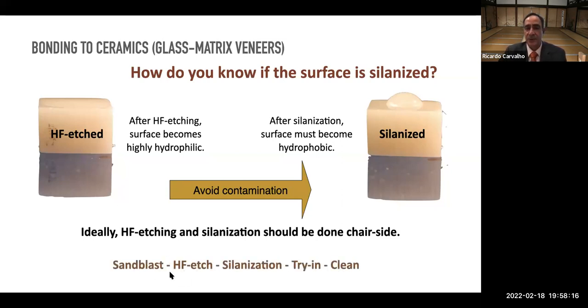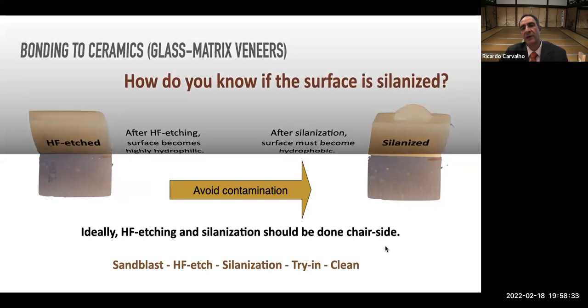The ideal protocol, or sequence, would be sandblast if necessary, then hydrofluoric acid etching, silanization, ideally done chairside, and then you can do your try-in, you clean, and then you are ready for cementation. You have to understand that silanization, the chemical reaction that occurs on the surface of the ceramic, is a very strong bond.